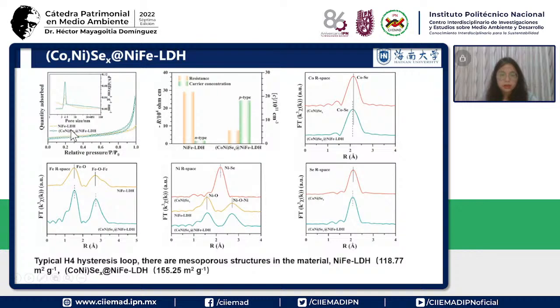And also compared to the nickel iron LDH, in these composites the BET specific surface area is much improved, increased from 118 to 155. And the interesting thing is when we compare the conductivity, this composite shows much lower resistance compared to only the LDH, and the carrier concentration is much improved. That means this material has better conductivity.